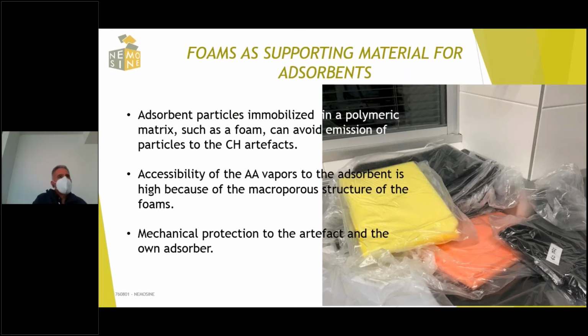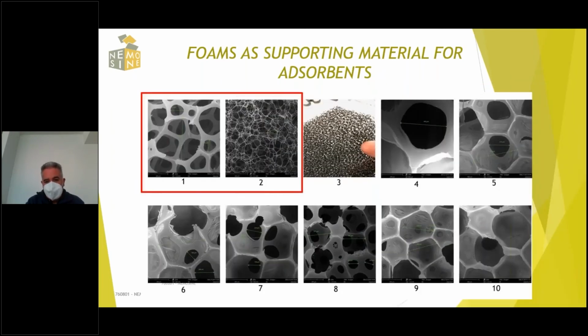Also, as I have commented previously, the foam by itself provides a mechanical protection to the artifact and the sorbent itself. These were some of the different foams that we tried to use from the beginning of the project. It was very clear that the open cell structures were the best ones. You can see, for example, in foams number 9 or 10, the typical closed cell structures. In closed cell structures, it's very difficult to have a good diffusion of the gas, of the vapor, because all the cells are closed. If you put our sorbents, our MOFs, inside of these cells, we can have a very good performance, but we have no diffusion of the gas, and this is a problem. This is why we selected open cell foams from the beginning.